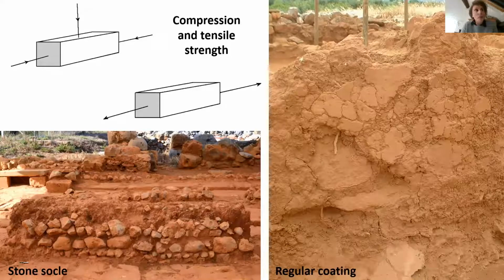Also, the often criticized limited resistance of sun-dried mudbricks to moisture can easily be dealt with. A stone socle can prevent erosion by capillarity and protect the mudbricks from potential floods. And wall erosion can be prevented by mud and/or lime plaster and by the regular maintenance of this coating.